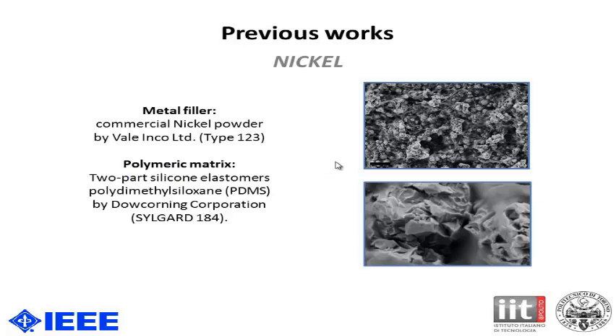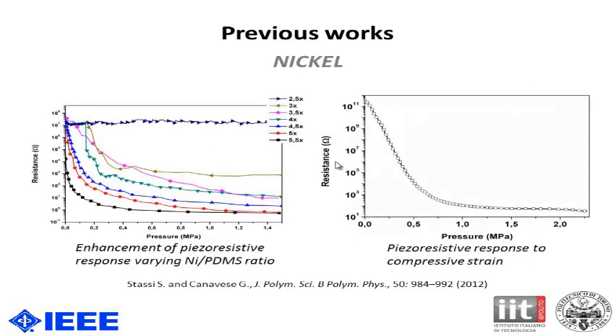In previous works, we did a work using nickel as a metal filler. You can see here the magnification with the SEM, and you can see that the particles are finely dispersed into the polymeric matrix. These are the results we obtained, and as you can see, varying the percentage of filler into the matrix, we obtain a different response to the pressure. The numbers up here mean that for one part of resin, there are 2.5 up to 5.5 parts of filler.